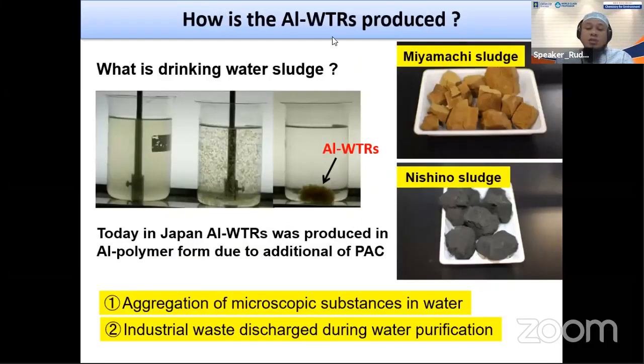So for example, this is cloudy water. When we add some aluminum water treatment chemical here, for example PAC, a common chemical we use to clean the water, it makes flocs during flocculation and coagulation. And this is the aluminum water treatment sludge. When we dry this material, we get this kind of material. For example, this is the Miyamachi sludge and this is the Nishino sludge.